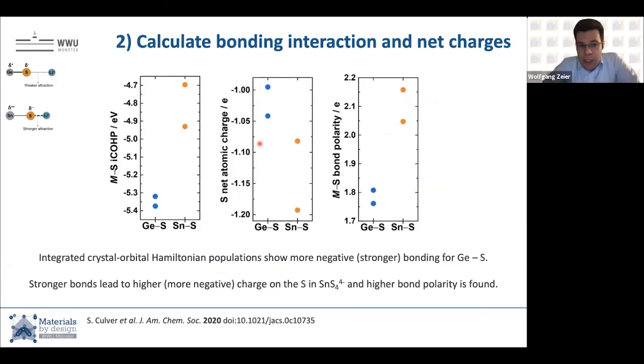What do we see in calculations? Well, it's a tricky question because it really depends on how to calculate these. And it took us a while to figure out how to properly assess these bonding changes. What Ben and a student did was calculate COHPs, so bonding overlap influences. And what we see is that the germanium-sulfur bond is more negative than the tin-sulfur bond, which suggests a stronger covalent bond for germanium-sulfur.